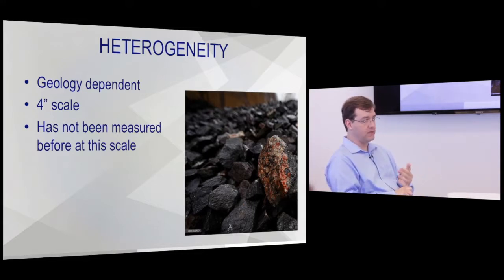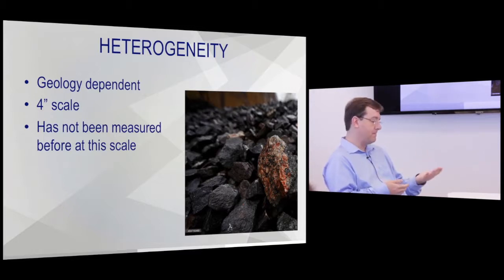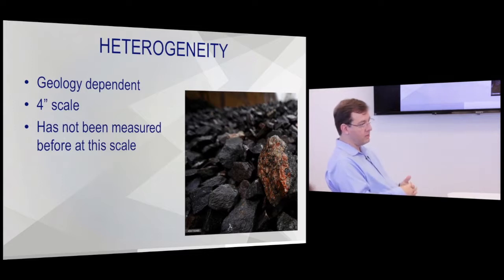It's more selective because it doesn't look at the average particle density, it looks at the density profile. So the average density could be low, but 5% of that rock might be in the target density profile range. And the sensor can say, well, yeah, it's a low density rock, but 5% here, this little crescent, looks like ore. And we know that ore is valuable enough to make that whole rock worth processing, so they'll take that whole rock and send it to the ore bin. Whereas DMS can't do that.